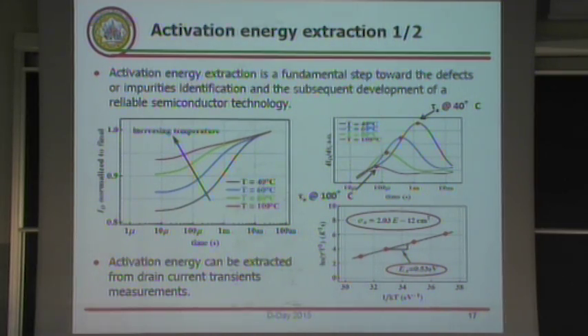So using this point, this emission time constant and the temperature, we can draw this Arrhenius plot, and the slope of the Arrhenius plot is the activation energy of the defect. We can also extract from the Arrhenius plot the capture cross-section. So using this procedure, we have a complete characterization of the defect.